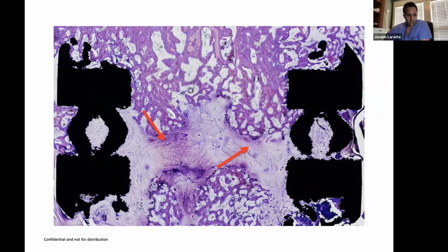So what we see here is that in between the cage, this is end plate up here, this is end plate down here, and this is in between the cage. In between the cage, we are seeing some sort of endochondral ossification. Endochondral ossification means that the bone is formed through a cartilaginous precursor. So in between the cage, we are seeing some early evidence of endochondral bone formation. Again, this is without any bone graft at all occurring through the cage itself. And if you look at the early Boden studies from the 90s about how fusion occurs, we don't necessarily know 100% how biological fusion does occur.